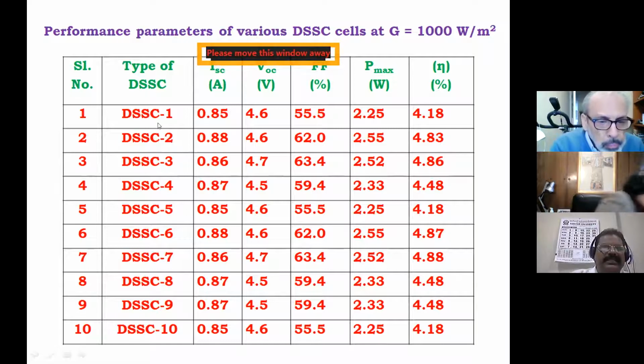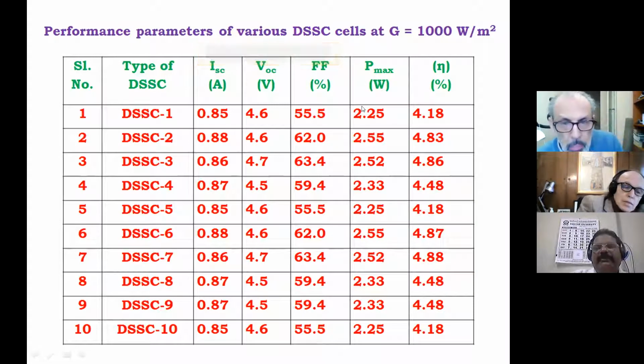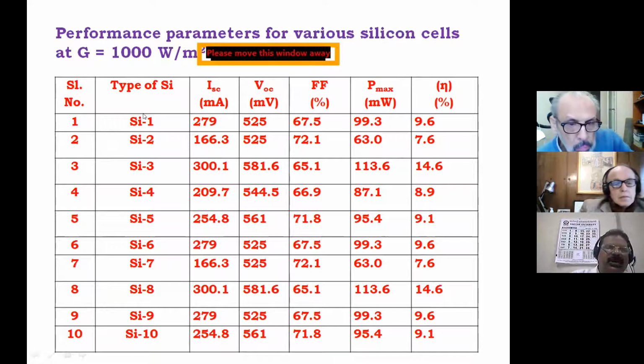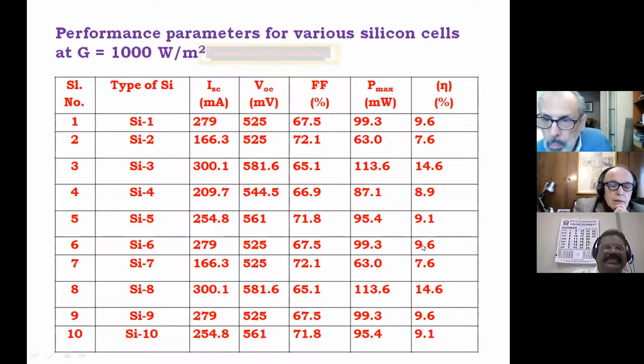Here again, the performance parameters for various solar cells at irradiance values of 1000 watt per square meter. For many types of solar cells, they have been aggregated and measured: the short circuit current, open circuit voltage, fill factor, and maximum power. With that, the efficiency is also calculated with naturally available sunlight. Similarly, many silicon solar cells we have purchased from China, with varying values of parameters, and we also identified different efficiencies with different fill factors.